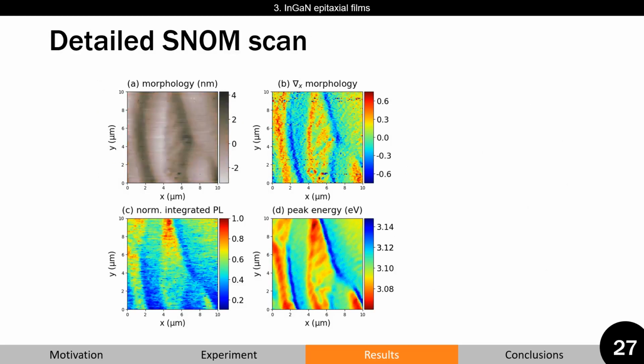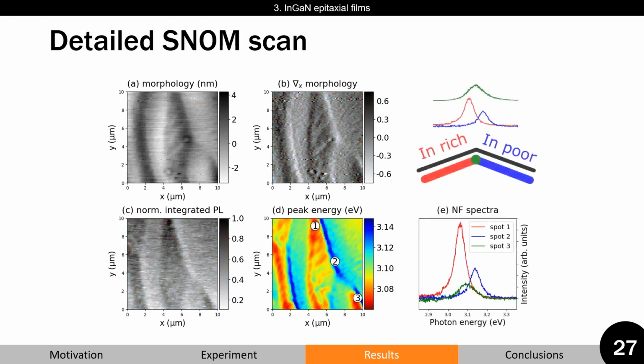By calculating the morphology gradient towards the x direction, we observe that the direction of the slope strongly correlates with both integrated intensity and peak energy. We can then take example spectra and observe that there are red-shifted indium-rich slopes which emit stronger emission, and there are blue-shifted indium-poor slopes which emit weaker emission.